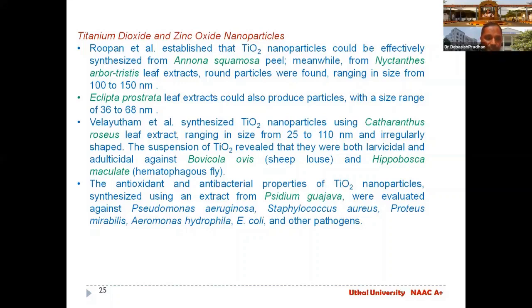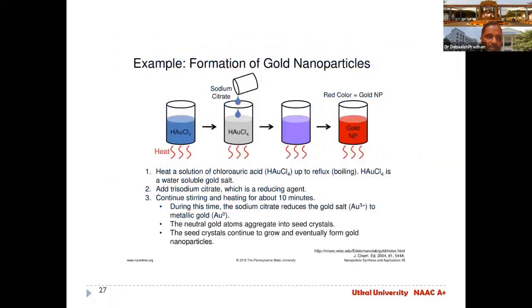So these are the recent approach in nanoparticles. You see, this is a formation of gold nanoparticles step by step. They have cited it like: heat a solution of chloroauric acid, that is HAuCl4, and after that reflux them, boiling them. That HAuCl4, chloroauric acid, is a water-soluble gold salt. Then add some trisodium citrate, which is a reducing agent.